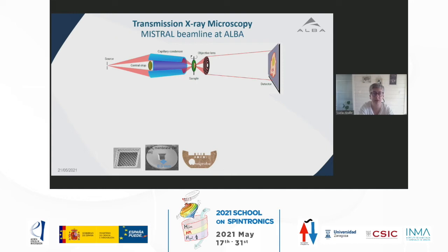So the kind of substrates that one can use are either electron microscopy type grids or silicon nitride membranes, or freestanding systems. Now there are many groups working on three-dimensional objects in magnetism to see the effect, for example, of the curvature on the magnetic interactions, geometrically induced DMI or geometrically modulated and so on. So one can use just half moon holders where the structures are freestanding. This microscope has 26 nanometer resolution in 2D and around 50 in 3D.